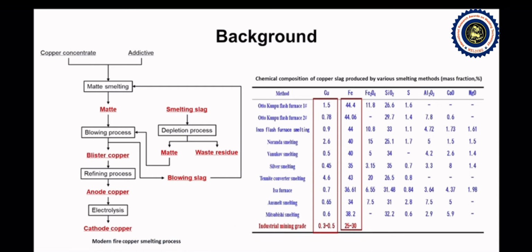Then, let me talk about the energy and environmental issues of the copper slag. In order to increase production capacity, high oxygen potential is now used in industrial copper smelting. This results in more valuable elements in the slag, no matter what process is adopted, as shown in the table to the right. The slag contains copper, 0.4 to 4.6%. The slag contains iron, about 40%. All of them are higher than the industrial mining grade, and copper smelting slag must be depleted and the copper recycled. Consequently, efficient utilization of copper slag is the inevitable choice for energy saving and emission reduction in China's copper industry.